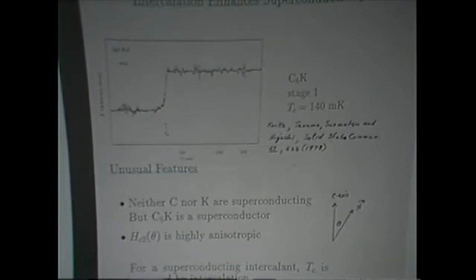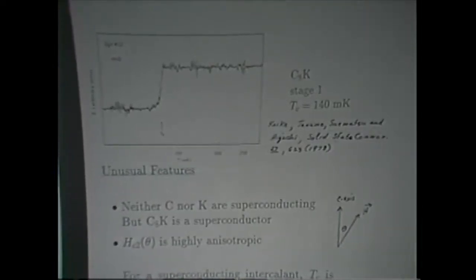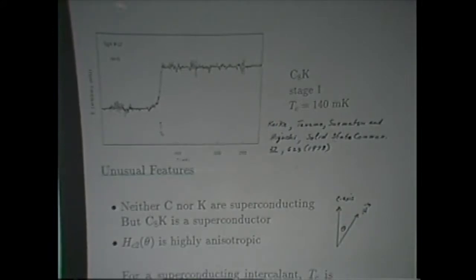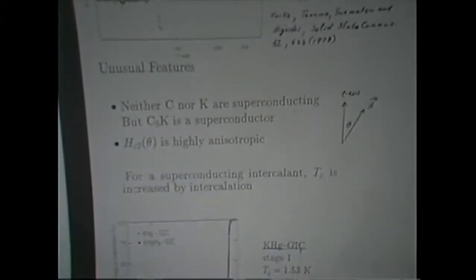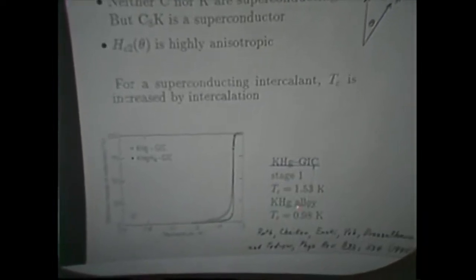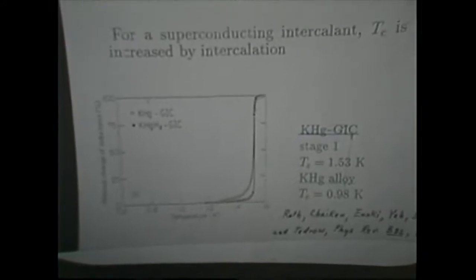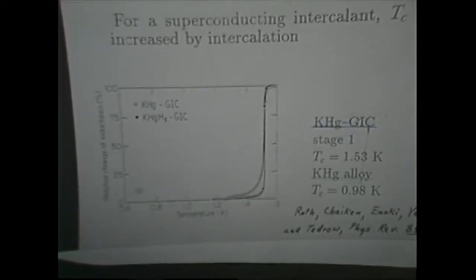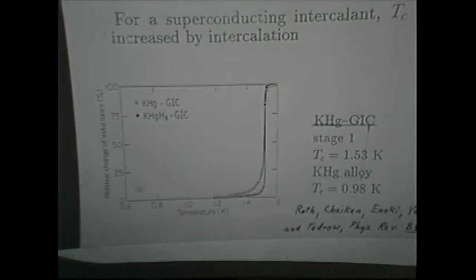One is that you can make something superconducting where the constituents are neither superconducting, and that's the case of the alkali metals. Here's an example, C8K, stage 1 potassium in graphite, and that has a pretty low transition temperature, but still, potassium isn't superconducting, nor is carbon. Now, take something that is superconducting, like potassium mercury, an interesting system. It has a transition temperature of about 1 degree Kelvin. You put it in an intercalation compound, and instead of 1 degree, you get 1.5 degrees. So for systems that are not superconducting, you can make them superconducting, and systems that have a low transition temperature, you can enhance it. So that's an interesting point. So superconductivity in intercalation compounds is something that is worth trying to understand.